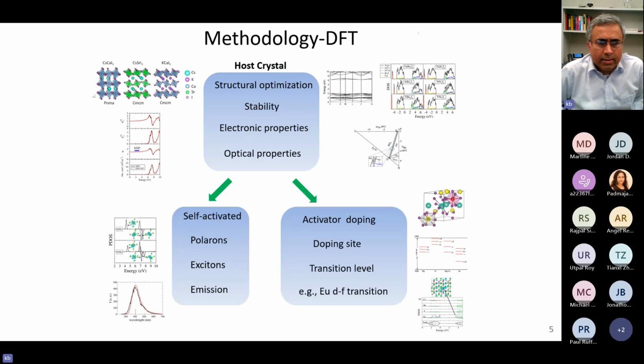So like I said, we do computational materials, which is based on density functional theory most of the time. And typically what we do, we start with a host crystal structure, and then we optimize the structure, and then we can investigate the stability of those crystals versus other possible secondary phases. And when we grow a crystal, it's very important to have pure crystals, and that's why their formation energy and their stability versus other competing phases is important.